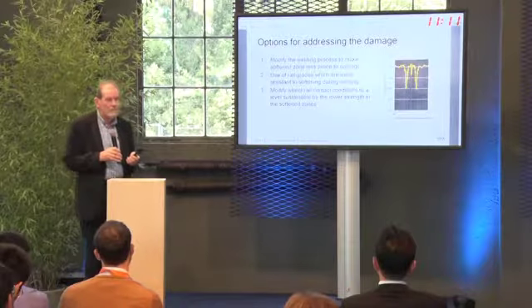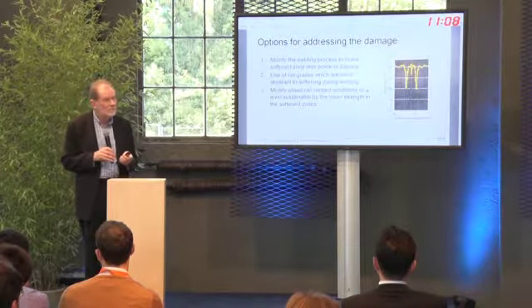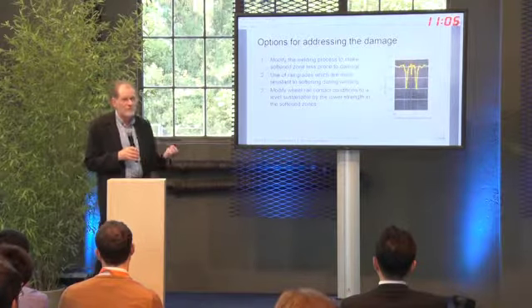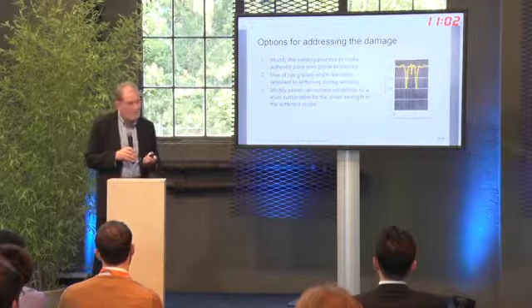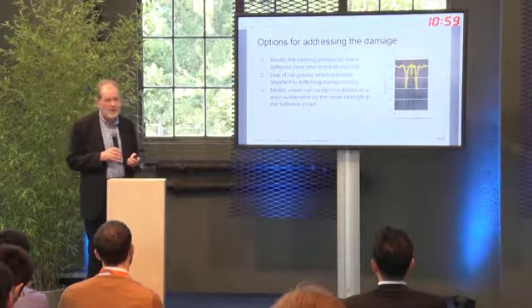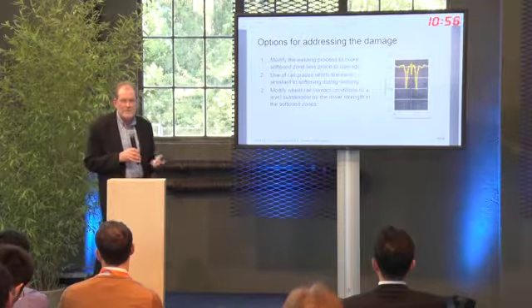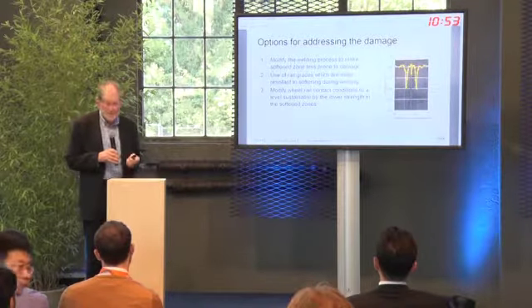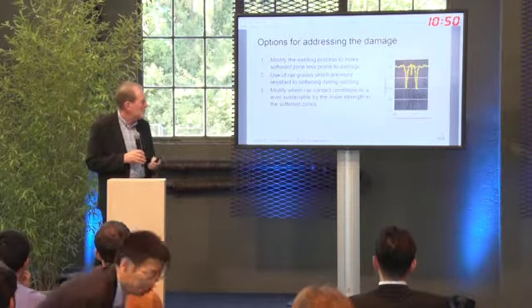One is obviously lower the contact stress levels at the gauge corner, or modify the creep conditions by putting in friction conditions at the gauge corner. These systems don't use any lubrication in those curves. There's a number of reasons for that. Historically, gauge face lubrication hasn't been particularly effective in those sort of operations because of the remoteness of it. And also, there's a reluctance to put anything on the rail that's going to compromise the available adhesion, if you're hauling a train that's about 50,000 tonne up a hill.